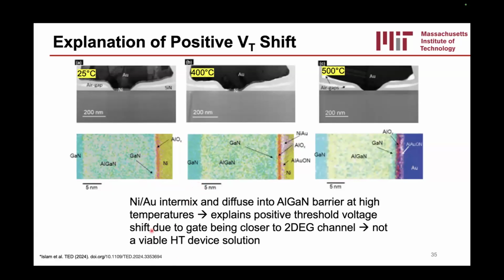And so people over at the AFRL have actually studied this a little bit and saw that if you get some nickel gold T-gate HEMTs and you start annealing them at 400 or 500 Celsius, the nickel layer right here, which is the Schottky contact, actually disappears. It intermixes with the gold, and both of them together start to really diffuse into the AlGaN barrier. And so that is going to affect your reliability.